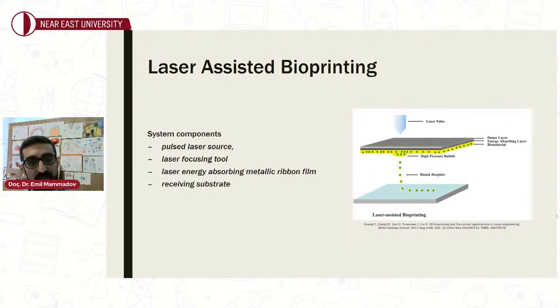The second type of bioprinting, and the most expensive one, is laser-assisted bioprinting. This is a very interesting technique. Here we don't have any nozzles. We have a ribbon, a pulsed laser source, and a laser focusing tool. The laser pulse hits the ribbon and forms a bubble, and that bubble drops onto the receiving substrate. When you do it in a fast and precise manner, you may form constructs.